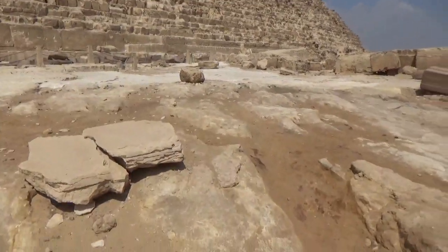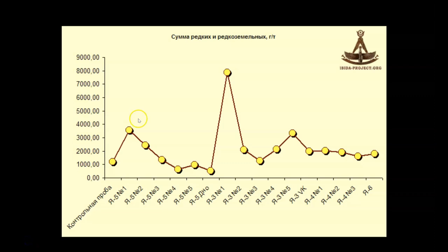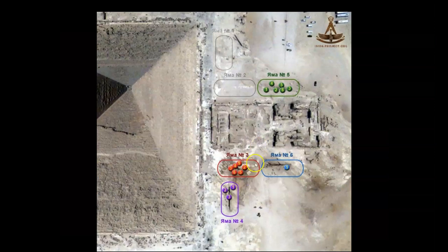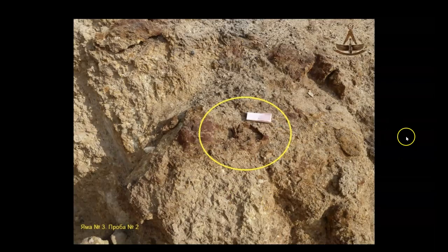Okay. All right, now on to the comparison of the trace elements and rare earth metals in these samples. First, you can see here a total sum of the elements in each sample, with one sample location in particular having significantly higher concentration, at almost 8,000 grams per ton, where all the rest of the samples were around 1,000 grams per ton. That particular sample was taken from pit number 3 right here, sample location number 2 right here, and this is what the area and material looks like at that location.